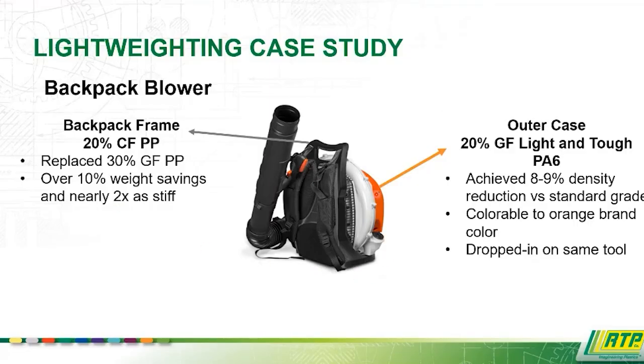And then with this orange colored outer case, we replaced the regular 20% glass fiber nylon 6 with our light and tough compound. We achieved that 8 to 9% density reduction. Was still able to get that orange brand color and a nice surface finish, not possible with something like carbon fiber, and it dropped right in on the same tool.